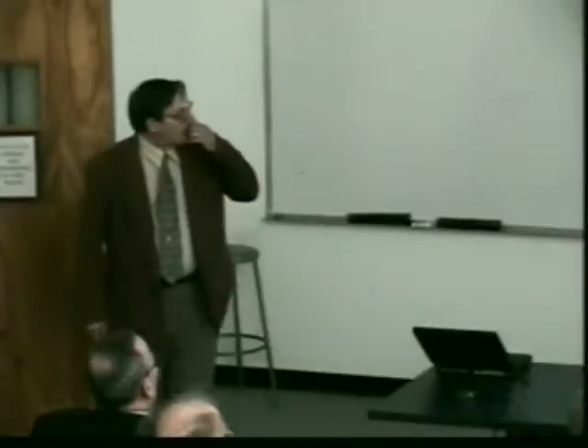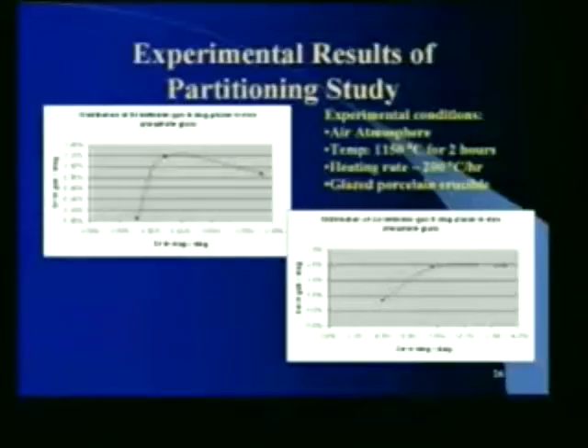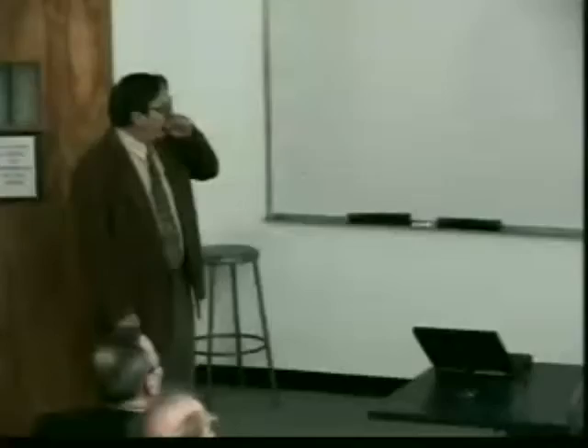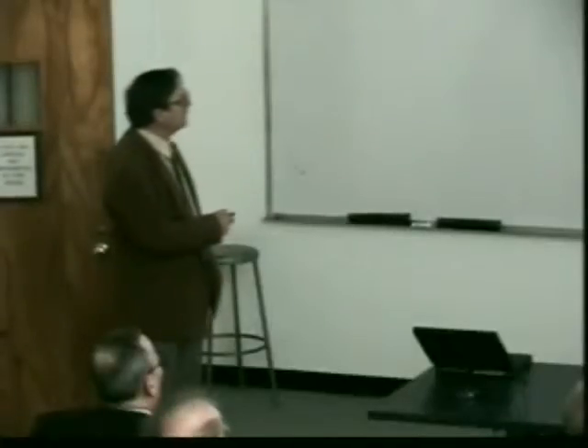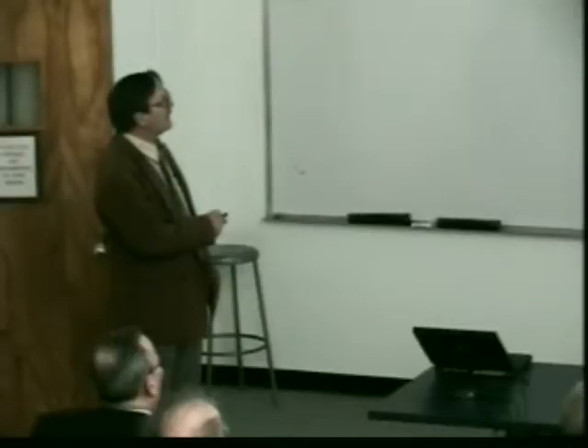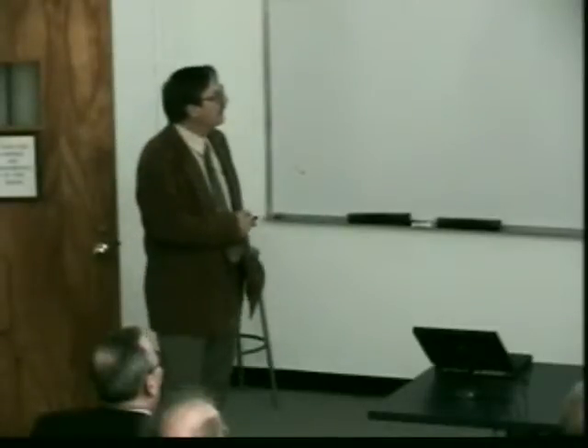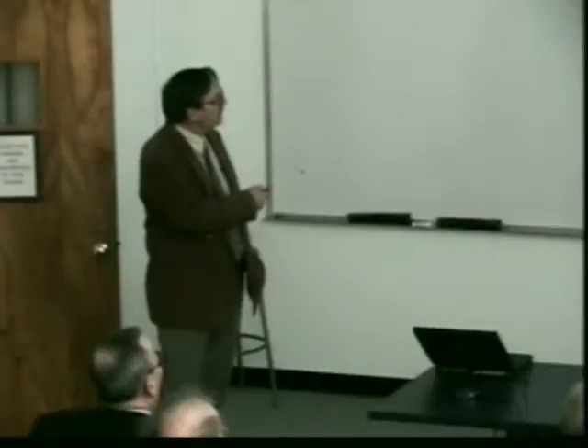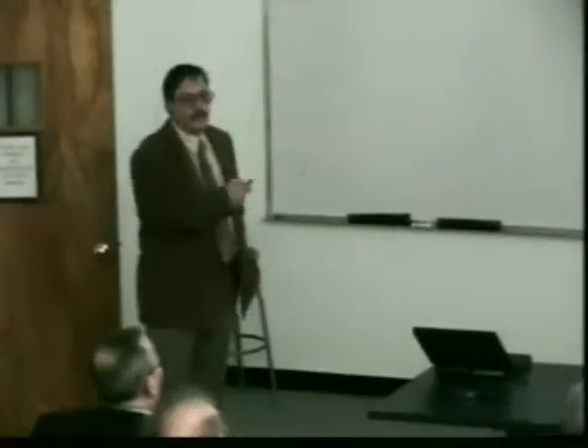A little bit about partitioning. One of the big advantages of iron phosphate over conventional glasses is, according to people at Rolla, University of Missouri Rolla, that work quite a bit on this, that they have a larger ability to accept strontium or cesium into the glass phase. And these show some partition experiments. This is the amount of strontium in the gas phase versus that amount in the slag or glass. And this is talking about 1% or 1.2%.